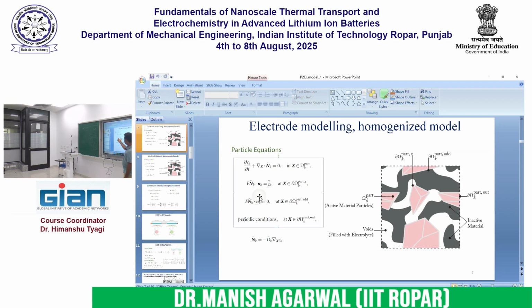The other condition, similar to the previous one, is that the flux is equal to the current divided by the Faraday constant. So n tilde dot Nk equals jk, the current that we just saw from the Butler-Volmer equation, divided by the Faraday constant, and that will give you the flux. And on this boundary, because these are not actual domain boundaries, these are only some portion of the domain that you have taken. The overall electrode is much bigger. So these are artificial boundaries that you have taken for the computation.